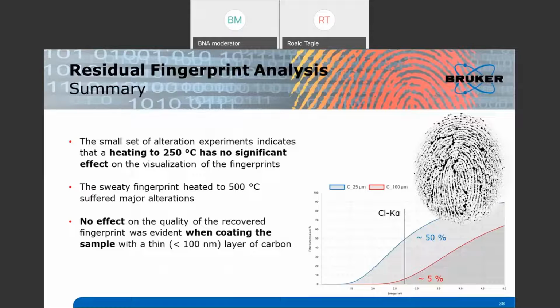We did a short experiment with a small set of samples, which we altered in different ways. The heating to 250 degrees seems to have no significant effect on the fingerprints, whereas the 500 degrees was too much for the one fingerprint we tested. We also found no effect on recovering a fingerprint which has been covered with carbon. We expect this carbon to be about 50 nanometers in thickness.